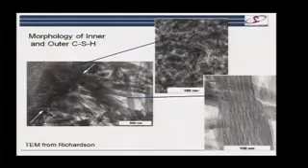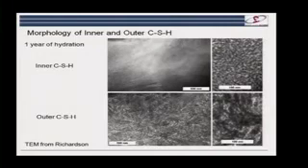Here's micrographs. Again, we can see the same kind of differences. And even that outer product will fill in over time, but there's still quite clear differences. You see here's an outer product, but it's really filled into a very dense structure, and this is an inner product here. And a lot of this is well established, but Eleanor's project will continue to look at these differences, and particularly to look at these differences as they pertain to how the calcium silicate hydrate changes when we put supplementary materials in like fly ash and slag.